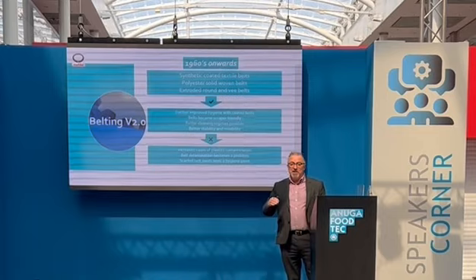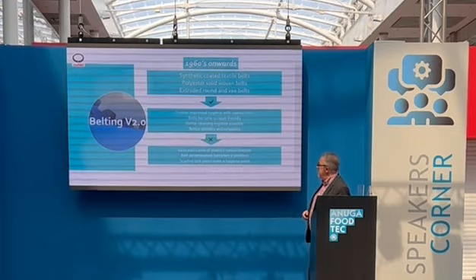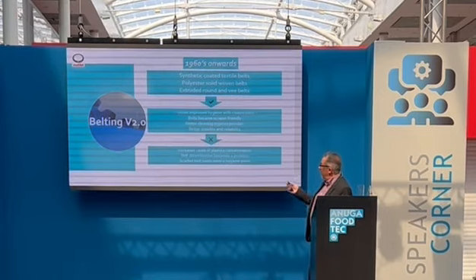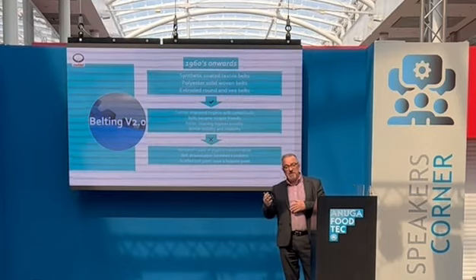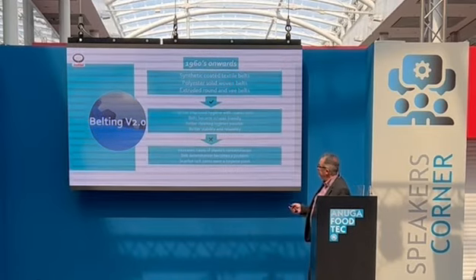Because the textile belts had laminations, they were made in laminates to increase the load carrying capacity. That was becoming a problem. They would separate and allow bacteria in between the laminates. And then, of course, you had a scarf belt joint. Instead of a finger joint, you had an overlap joint, and when that started to fail, you would then have a little pocket where bacteria would creep in.